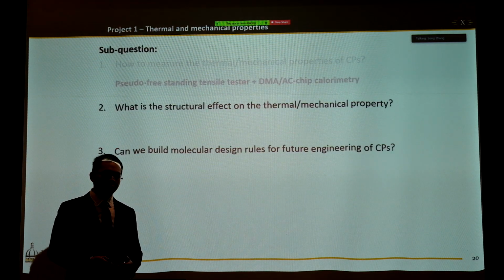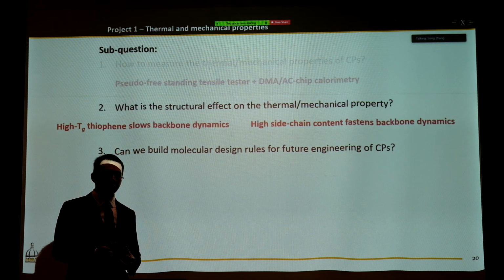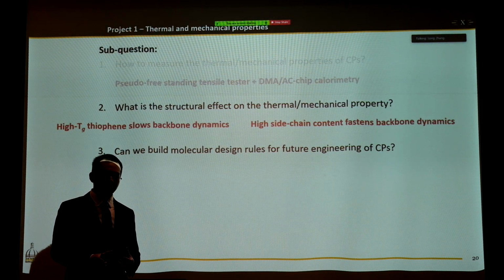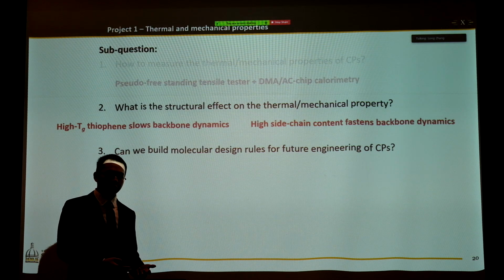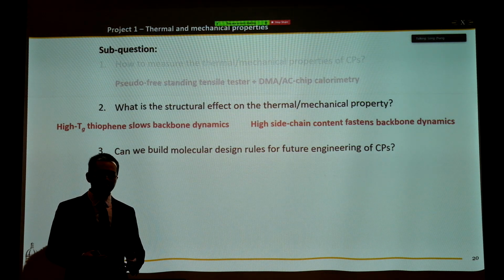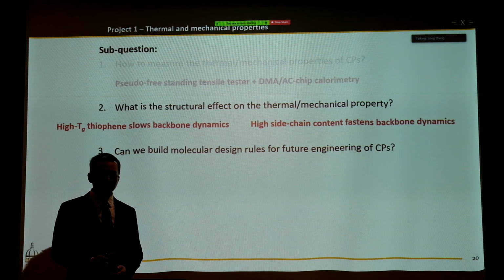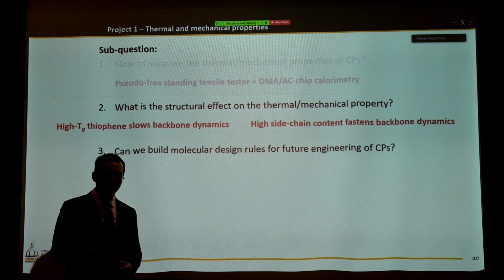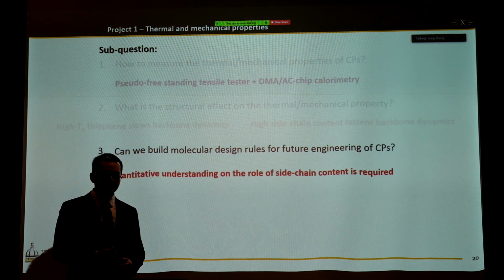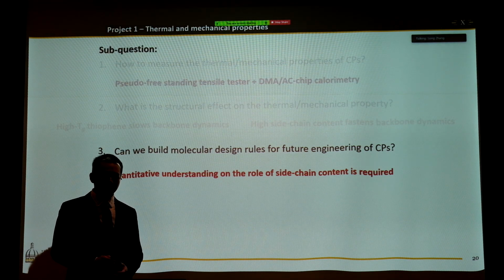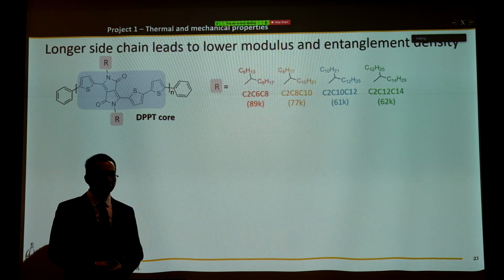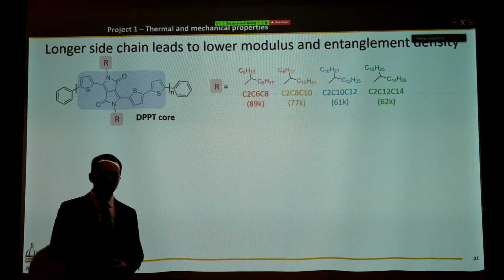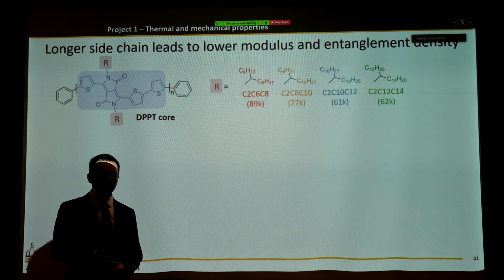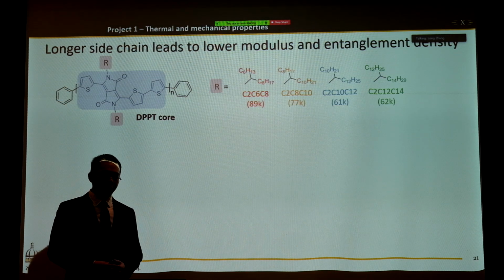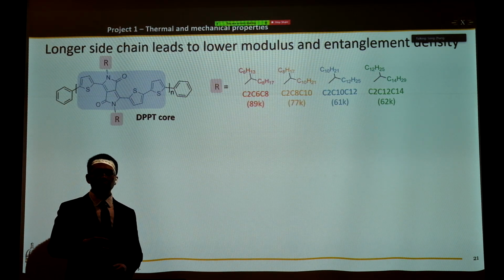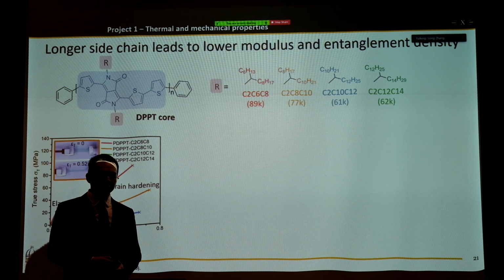Okay, now we understand the backbone dynamics can be affected by a high-Tg thiophene and low-Tg side chain structure. But we still do not know how systematically the side chain content will affect the backbone dynamics. And that is the next project. So with that in mind, we designed these following 4 polymers based on the DPPT polymer backbone. With increase in side chain length from C2, C6, C8, all the way to C2, C12, C14, we see this